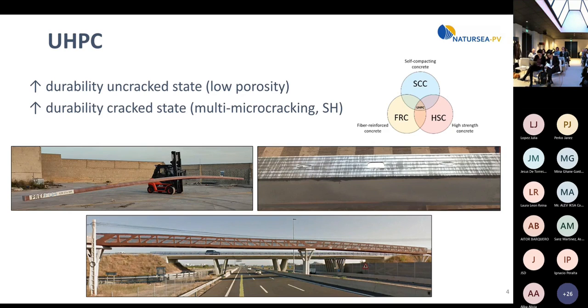It was mentioned before that UHPC is flexible. It is and it isn't. The material itself is stiffer than normal concrete because the Young's modulus is higher. But as the performance is higher, we can design structures with less material. So the result is that the structure can be more flexible because it is more slender. You can see an example of one of the beams that we produce in the factory. This beam has a slenderness of 150, and the structure itself is very flexible. When we bend it a lot, the deformation is significant. And as I already mentioned, instead of one macro crack that is already a problem for the future, we have multiple micro cracks of 20 or 30 microns that really close when the beam comes back to the normal position. So it's flexible and it's durable.